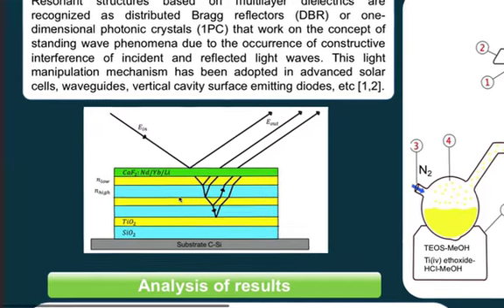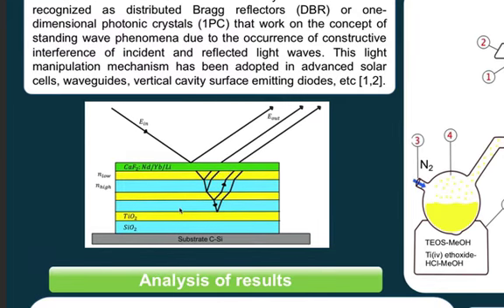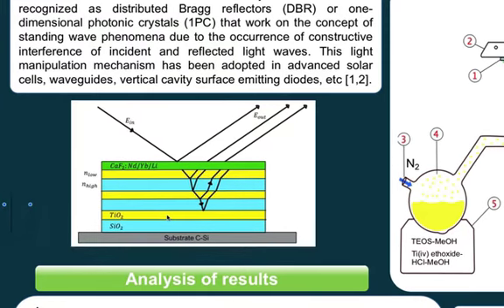In this case, it was chosen that the alternate layers would be silicon dioxide and titanium dioxide. This is because these materials have been extensively studied. There was already previous work carried out by the working group. One of the main characteristics of these structures must be the notable difference between refractive index of the materials. In the visible and infrared regions, the refractive index of silicon dioxide is approximately 1.45, and for titanium dioxide is 2.35. And this is good for constructive interference of light at fewer layers.